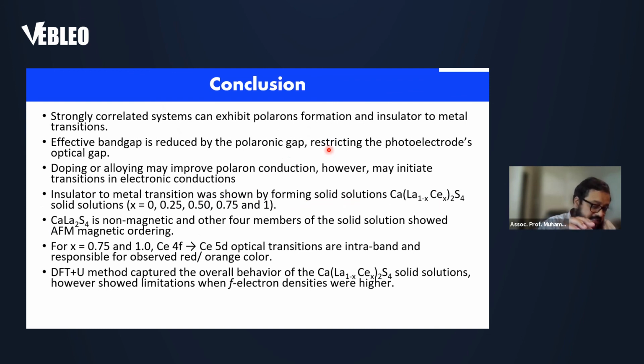So in conclusion, this is a general conclusion that we know that a strongly correlated system shows many exotic phenomena. We basically studied and presented two phenomena that are relevant to photocatalysts. One is polaron formation, another is insulator to metal transition. We try to argue that the effective band gap can be reduced by the polaronic gap, in addition to slower electron mobility or hole mobility, which restrict the photoelectrode's optical gap.